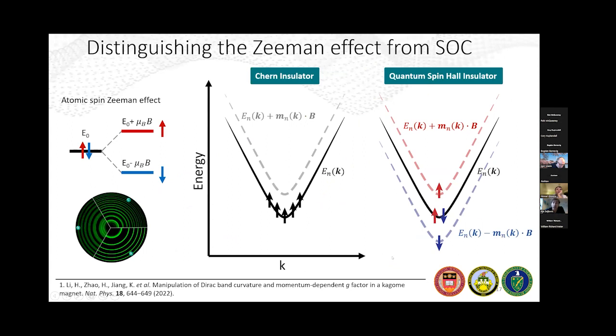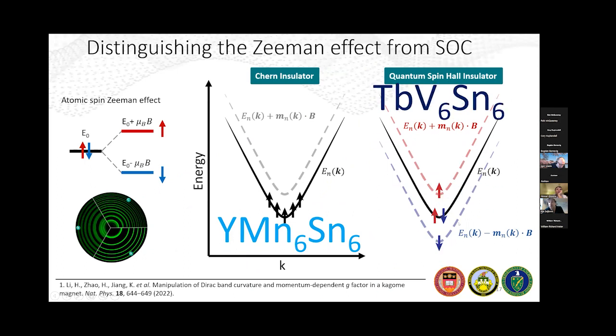The second system is unlike this yttrium manganese tin, where you have a single spin polarized band that, as you apply the magnetic field, might shift upwards or downwards. In our case, it shifts upwards. On the right side, I'm showing, and I will explain more, the case of terbium vanadium tin, where you have a nearly spin degenerate Dirac cone. Even though it's spin degenerate, you still have spin Berry curvature, primarily at the bottom of this Dirac dispersion. As you apply the magnetic field, you actually get a splitting. We see two spin branches of the Dirac dispersion, one moving up and the other moving downwards as a function of magnetic field.